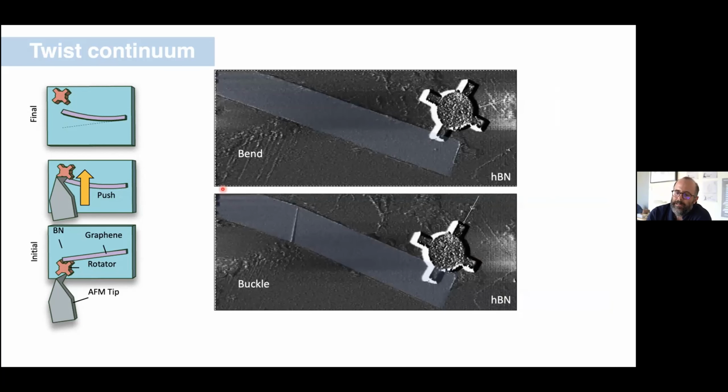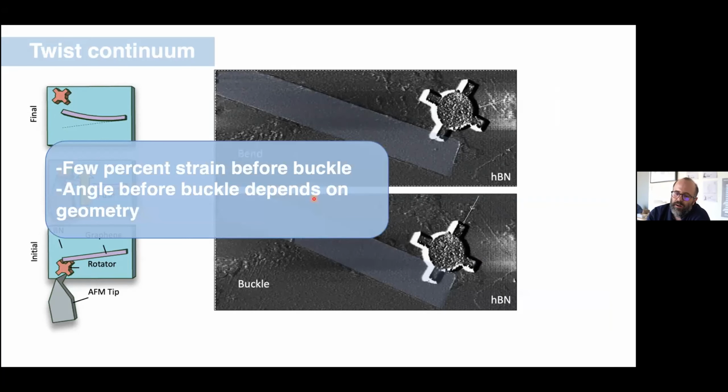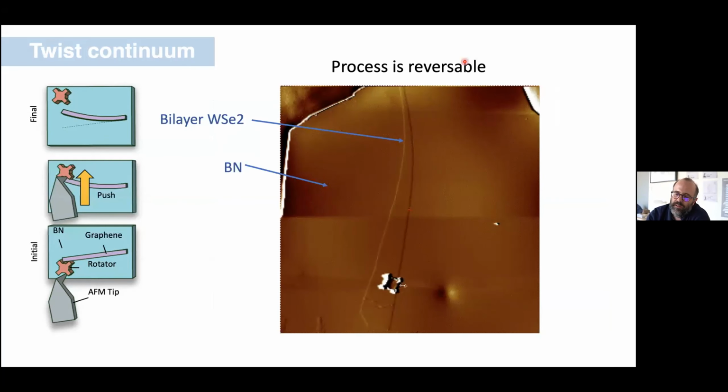Okay, cool. The bending mechanics is very similar to the bending mechanics of a simple beam. If you bend too far, the beam will buckle. It does this because you exceed the allowed strain deformation that you can put this beam through. So here's an example of that. It turns out that if you marginally buckle, so here is another image of bending one of these nano noodle beams, if you go just to the point of buckling, you can see it right where my mouse is. At the extreme, it starts to buckle, but not too much.